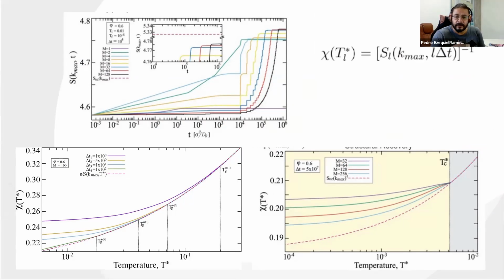In the figure at the top, you can see the relaxation of the maximum of the time-dependent structure factor for different cooling processes. The inset shows a zoom of the final state, and we can see that there are different final states for different processes. The dotted line in the inset is the expected equilibrium state. As you can see, the theory predicts a cooling rate dependence of the final arrested state.